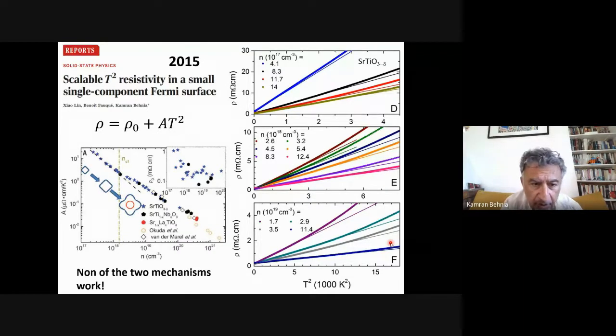And if you now plot A as a function of n, first of all, our data joins what was obtained by other groups. This is Tokura's group, obtained in the 1990s. This is Van der Marel's group. These symbols are our data, for both reduced strontium titanate and niobium-doped strontium titanate. And here is the interesting thing. In this part, the Fermi surface is single component, and it is very small. And the T-square behavior survives.